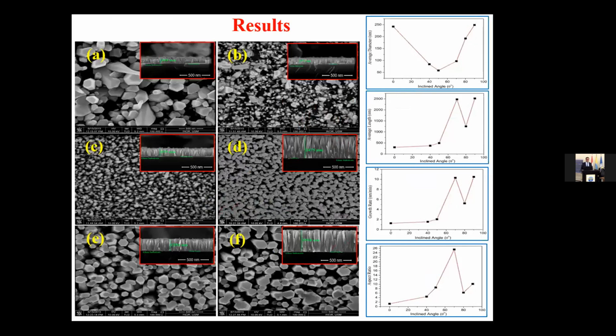The results: this figure shows the top view and the cross section or side view FESEM morphology of the different substrate inclined angles. A for 0, B for 40, C for 50, D for 70, E for 80, and F for 90. From all these figures, we can conclude that the substrate inclined angle has a remarkable effect on the surface morphology, such as size, shape, diameter, density, distribution, alignment and hexagonal shape of the zinc oxide nanorods. We can also conclude that the zinc oxide nanorods gradually improve as the substrate inclined angle increases from 0 to 90.